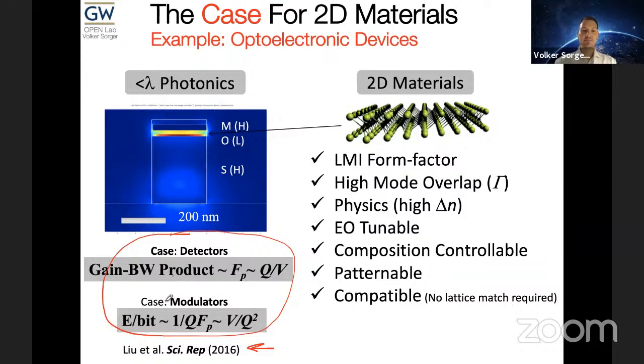For instance, in a modulator, you want to have a lower energy per bit, and the energy per bit improves with something known as the Purcell factor. The Purcell factor is nothing else but the Q factor of the underlying system divided by the mode volume. V is the mode volume, which suggests if you have a very small material or small optical mode, you can basically have a very efficient device. Similarly, the gain bandwidth product of a detector can also be improved with the Purcell factor. So 2D materials are very synergistic for these sorts of nanoscale modes.